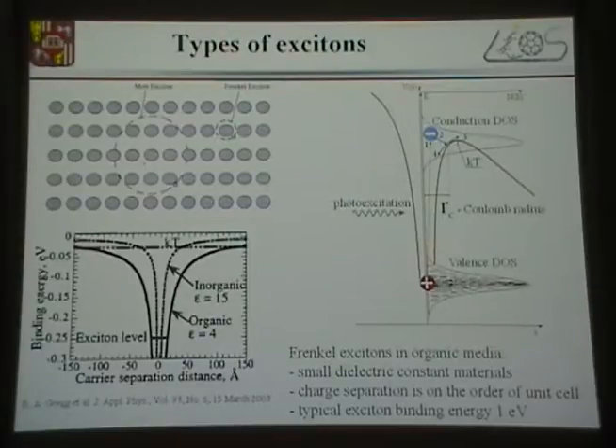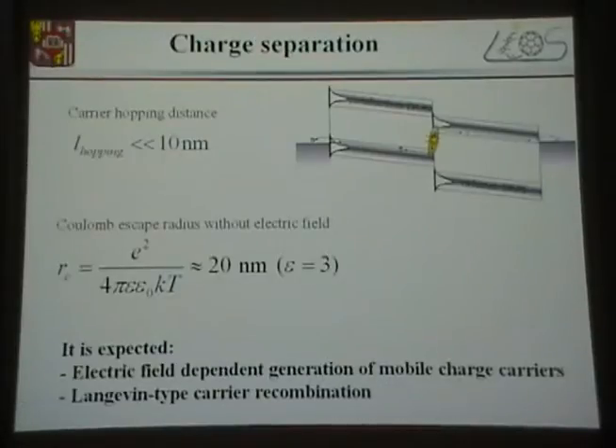And the way I like to see it is like this, the Coulomb. This is the typical, well known Onsager photogeneration model, which has been shown in selenium originally. Onsager photogeneration model with the applied electric field, and here we have a LUMO and HOMO density of states, and this is the photogenerated charge carrier. And the only way for the charge carriers to separate from each other is if the charge carrier is able to make it to a distance further than the critical Coulomb radius RC. Okay, so this is the requirement for the charge carriers to be separated. Otherwise, if they don't make that distance, they will simply recombine geminately.